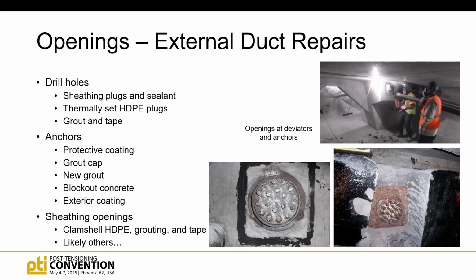So on the repair side of the externals, for drill holes, what I've seen, and I think this varies across the industry, is they'll take a piece of the sheathing, cut it, and then embed it in sealant. I've seen that. The more common one I've seen is they'll do thermally set HDPE plugs, where they basically get a plug down in there and heat it up and it fuses, and then they cut it off. There's also grouting and taping that can be used, where they put the clamshell back together, grout it full, and tape it up. So there's kind of multiple versions of that story.